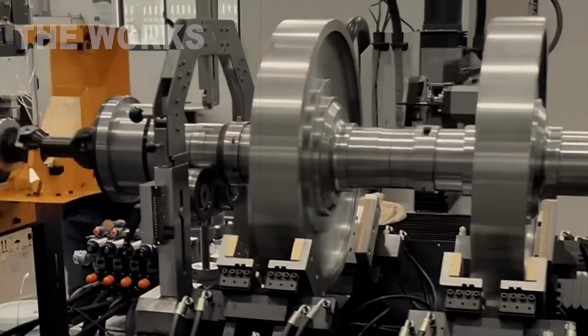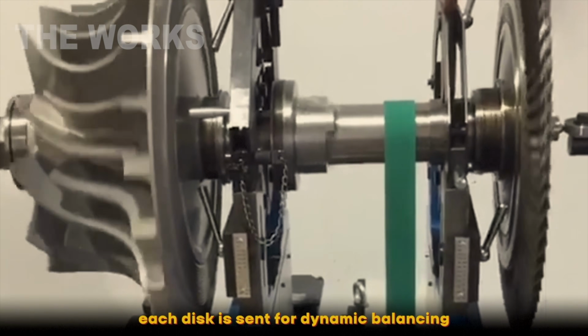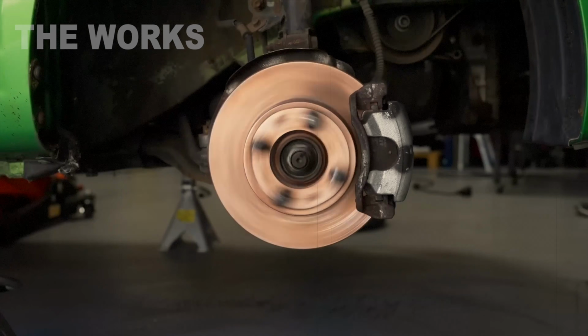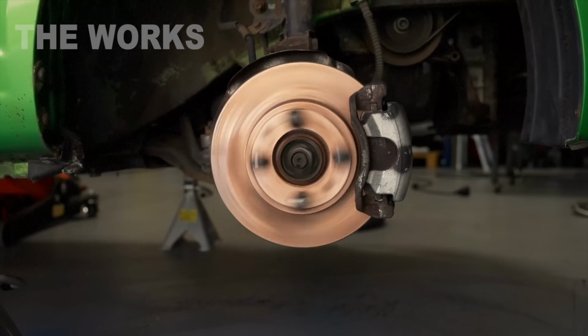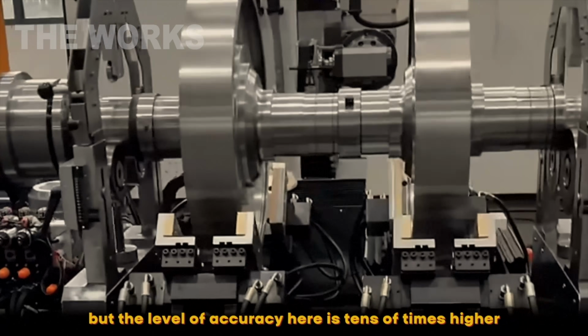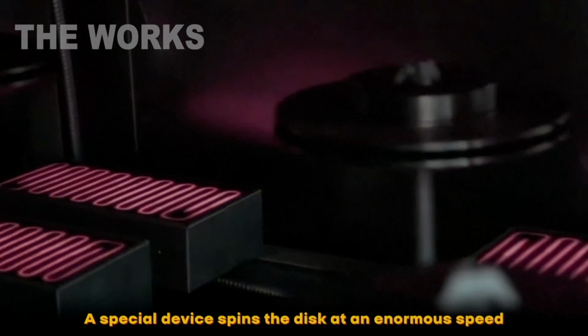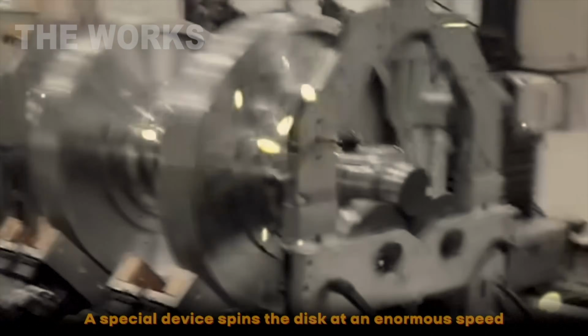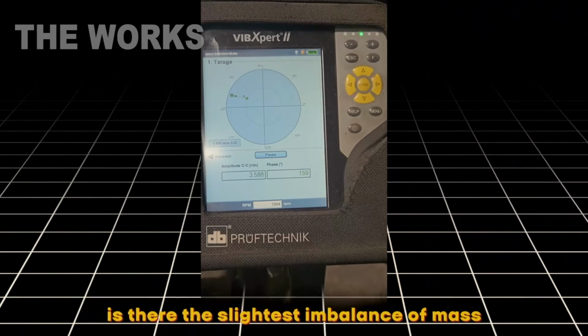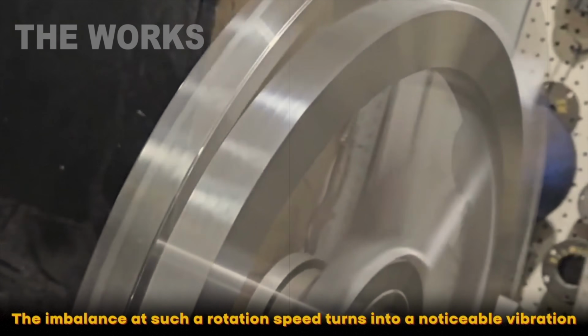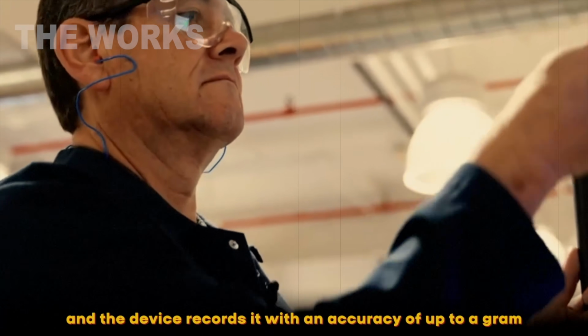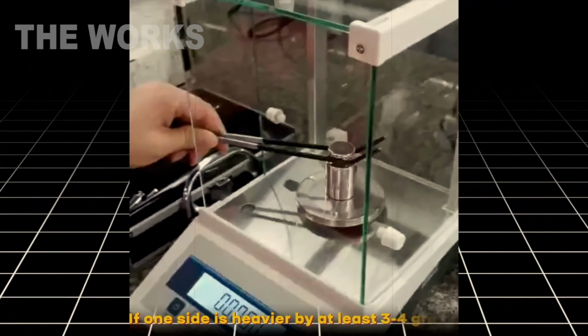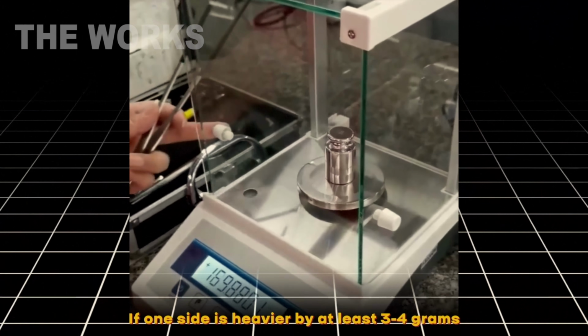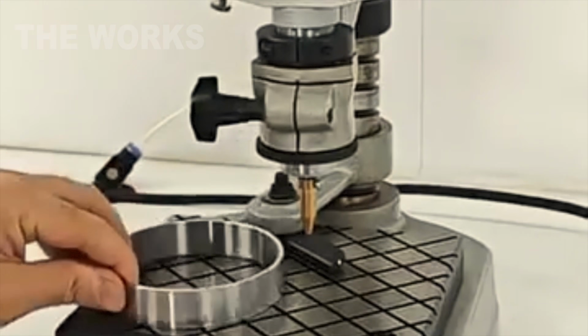Once all the excess shavings are removed, each rotor gets sent to dynamic balancing. It's a lot like what they do to your wheels at the tire shop, but the precision here is tens of times higher. A special device spins the rotor up to enormous speed and uses sensors to detect the slightest weight imbalance. At these rotational speeds, any imbalance turns into noticeable vibration, and the machine picks it up with gram-level accuracy. If one side turns out to be heavier by even 3 or 4 grams, the machine automatically drills out a tiny, nearly invisible dimple in just the right spot on the face to even out the weight.